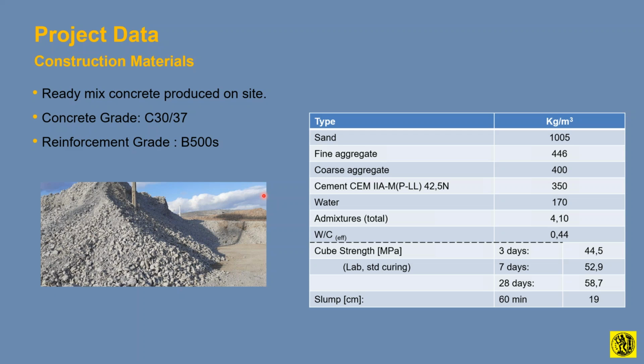The concrete is slip-forming suitable concrete. So the requirements were with several admixtures which are being used. The concrete has to have a fairly fast, early strength so that it can support the slip form operation. And it has to be, over the height of the slip form at the top of the form when it is cast, fairly workable, so that the operation, on a non-stop continuous casting operation, can accept the remaining concrete layers as they come in.